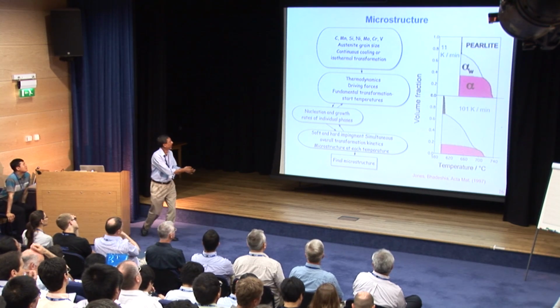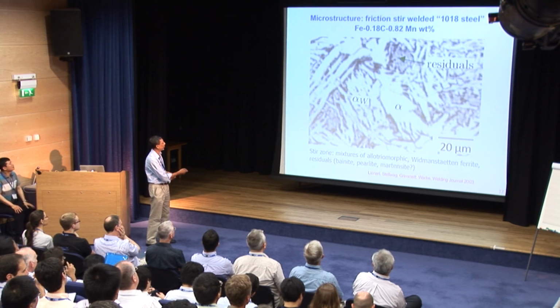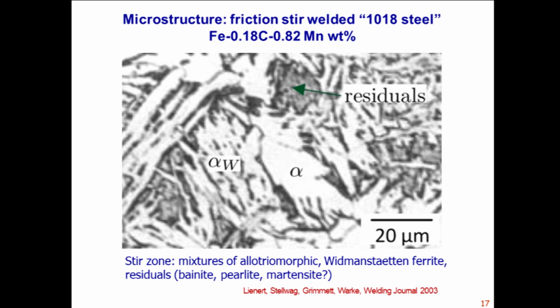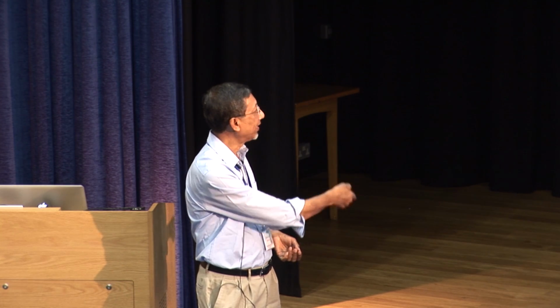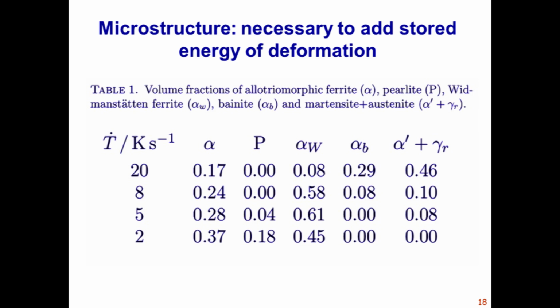And here is a microstructure that shows exactly that. This is reported in the literature in Welding journal, and we are able to predict qualitatively these microstructures. Quantitatively, we have done some calculations, but it needs to be experimentally validated by detailed quantitative metallography. That work will be done later on.